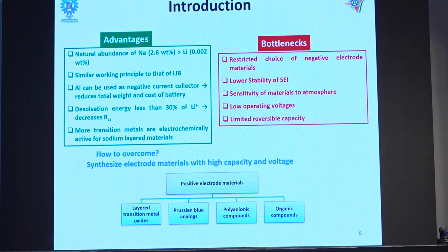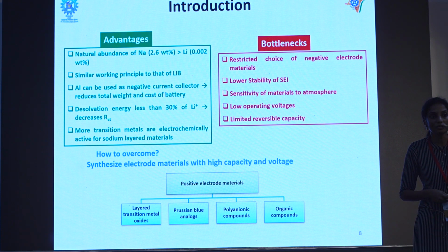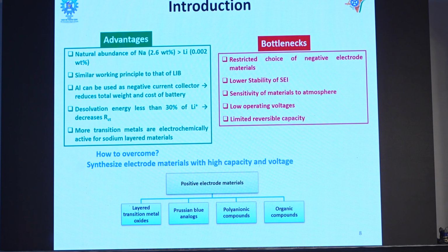And one major challenge that the R&D groups are facing is the sensitivity to humidity. If you make a sodium ion battery electrode and a lithium ion battery electrode, the lithium ion battery electrode you can keep for several years outside. But if you make a sodium ion battery electrode material and keep it for a couple of months in a normal atmosphere, I mean, we are all living in a humid atmosphere, right? Look outside. It has a tendency to react with the humidity from the atmosphere, and it will totally change the crystal structure.